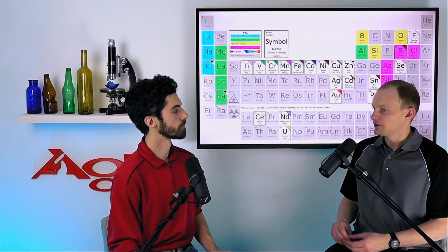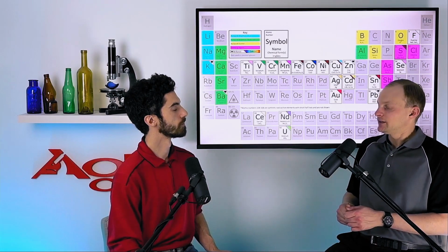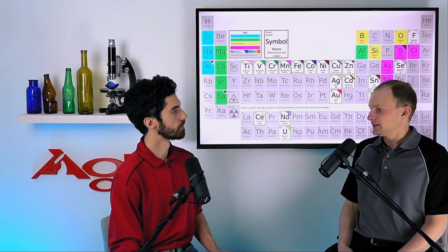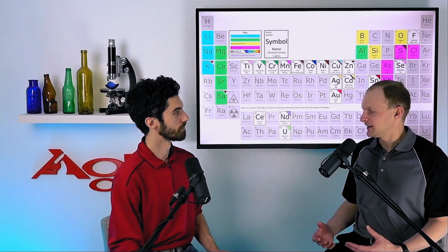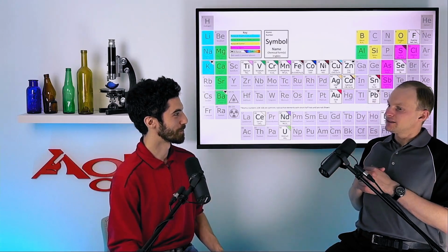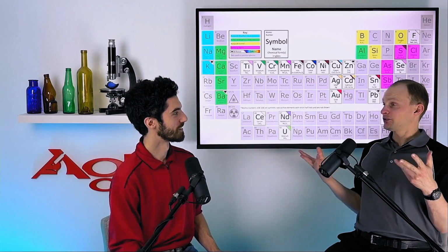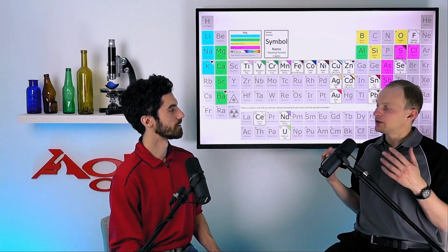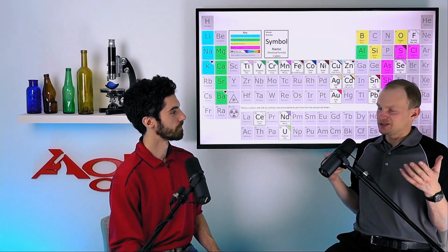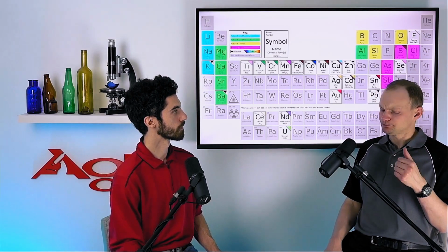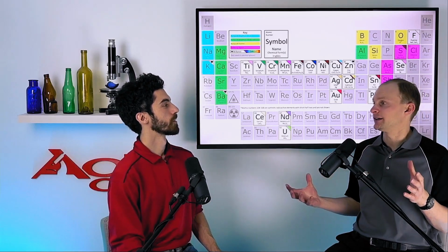Whereas with things like plastic, we're actually changing how long those chains of carbon atoms are, and there's no way to get rid of impurities. So with glass, let's say we have a bottle, it has labels on it, it has somebody's spit in it, it's got whatever gunk left over of the product, gum stuck to the bottom. That whole thing is going to get ground up, and it goes into a furnace, which is going to just incinerate all that stuff, and it just turns into CO2 because that's all organic matter. So all of our contaminants, typically just the organic stuff that it's going to pick up, basically goes up a smokestack, or it somehow gets reclaimed, but it's not going to end up in our final glass because it's made up of these oxides.